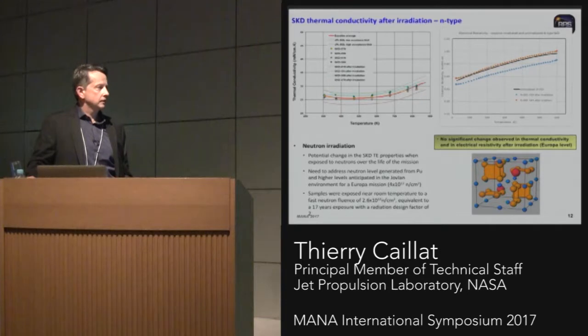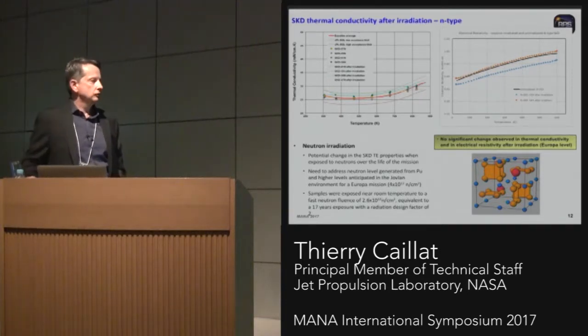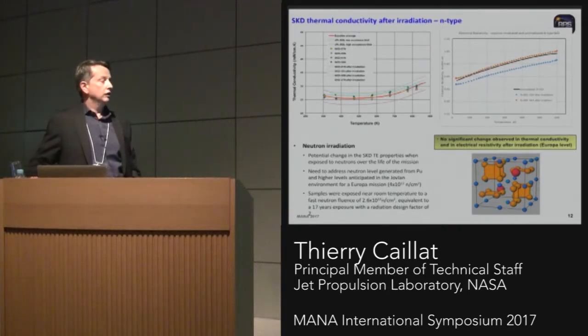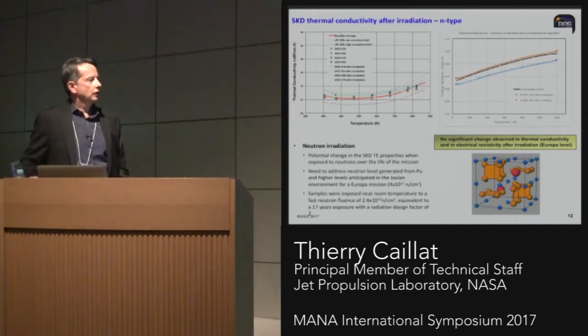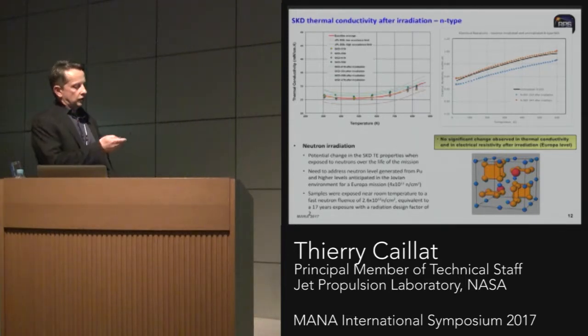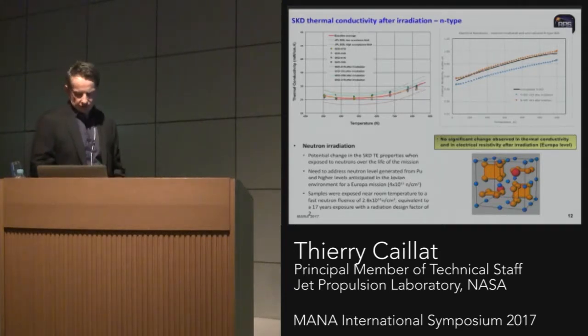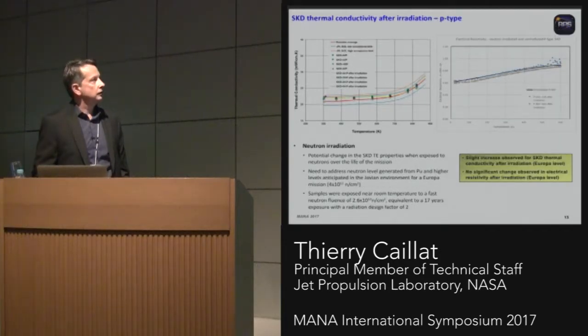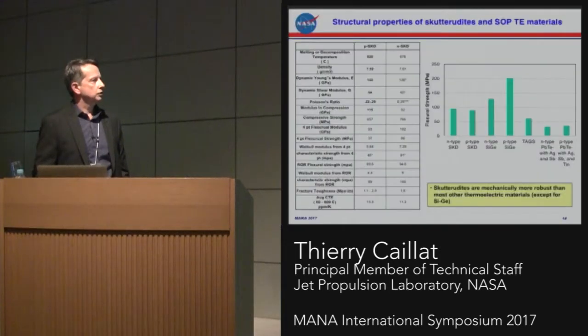So this is kind of a worst case. If you actually do this at high temperature, you can get help if you're creating some defects from self-healing at high temperature. But you can see that within sort of a measurement certainty, we don't see any change, which has been the case for all the thermoelectric materials in the past for the type of flux that we expect or the irradiation environment. But essentially, that was needed to verify. So the skutterudites actually are doing good for this. This is the P-types, so same conclusion here.